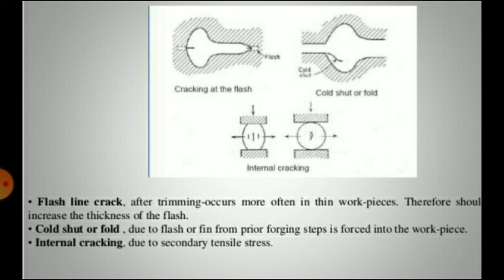Flash line cracks after trimming occur more often in thin workpieces; therefore, the thickness of the flash should be increased. Internal cracking is due to secondary tensile stress.